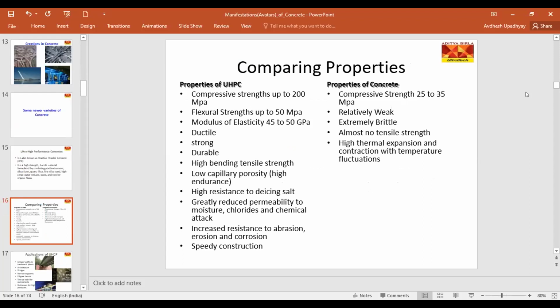If you look at the compressive strength, normal concrete is 25 to 35 MPa, whereas UHPC compressive strength is up to 200 MPa. Flexural strength is 50 MPa, whereas modulus of elasticity, that is E, is 45 to 50 GPa. It is highly ductile, strong, durable, with high bending tensile strength, high resistance to salt, increased resistance to abrasion, speed in construction, and it greatly reduces the permeability to moisture, chloride, and chemical attack.